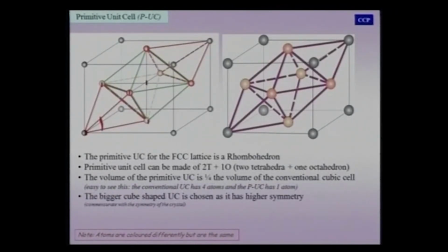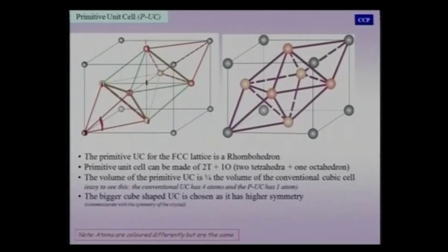Now, the reason we usually do not choose this unit cell for the cubic structure is because the unit cell itself has lower symmetry than the crystal, which as you can see has a 4-fold symmetry and actually has a 4/m 3-bar 2/m point group symmetry. So, we will take up the same structure using a model so that we can understand it slightly better.